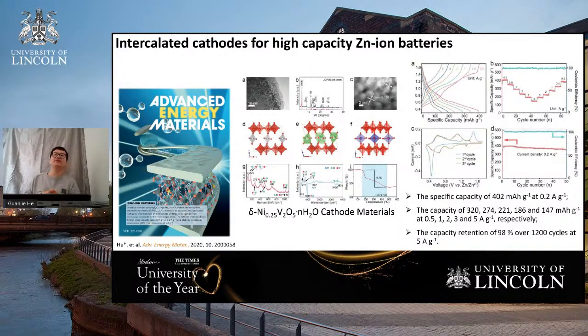And so we also try to evaluate the capacity at the different current densities to evaluate the rate performance. So what does the rate performance mean? Maybe you have already heard about the fast charging batteries. Probably we can charge our mobile phones for 20 minutes and then use for half a day or even 1 day. That means we need the fast charging batteries. And if we use a high current density to charge our batteries, firstly, we need to consider the safety issues related to that. Will the short circuiting happening? And the second one is how much charge we can put in these batteries compared to the low battery charging rate. And the rate performance is to evaluate such parameter.